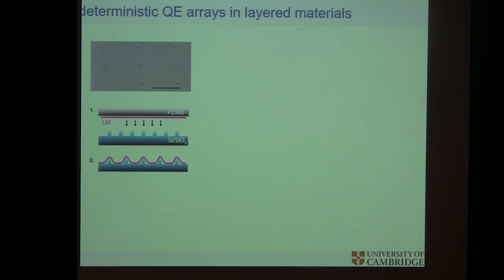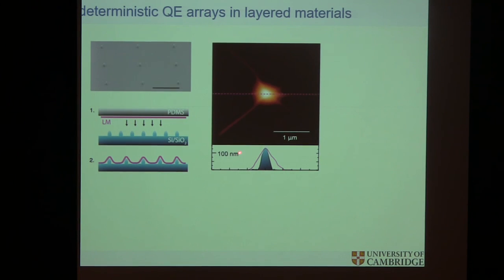And it turns out, when you do this, either you pierce, the needles are too sharp so the material actually goes through, but if it doesn't pierce, then it tents like this. So this is an AFM scan of the needle plus the WSe2 on top of the needle. So you can imagine what's happening. Beyond here, the material is on the surface, but up here, this is a tent. The whole tip of the pillar is being stretched. The material on the tip is being stretched by the weight of the remaining parts. It's a tent. And so right at the top, we have a strong strain present.